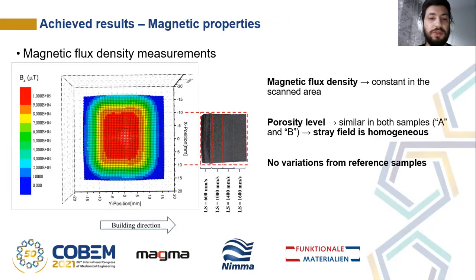The magnetic flux density measurements at the surface of both A and B samples revealed that the magnetic flux density is homogeneous. As presented earlier, the geometrical density values are similar for both samples, leading to similar magnetic properties. Although the SEM observations revealed this different porosity level, this was not sufficient to promote variations in the stray field.